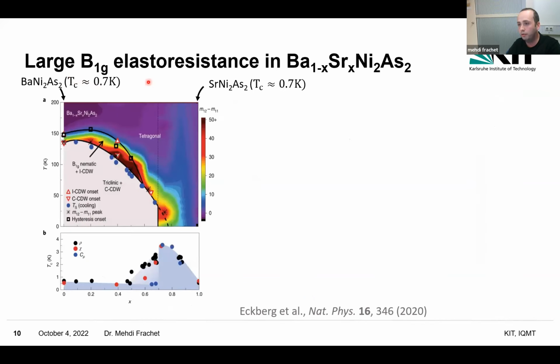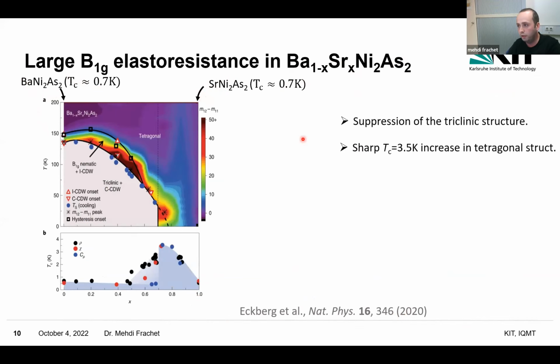So to come back to this slide, this very important result in strontium-doped BaNi2As2 was obtained two years ago by the group of John Paglione. What they did is study the complete series from the barium side to the strontium side. And first, two things to notice: using strontium, what they could do is completely suppress the triclinic structure.